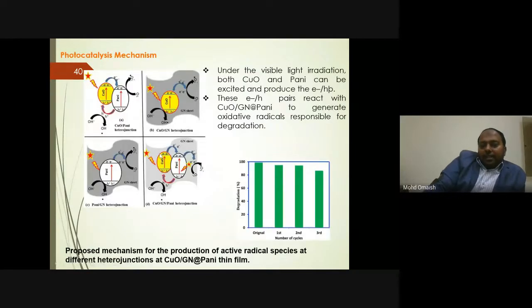As far as the photocatalysis mechanism, we propose four different types of heterojunction: the copper oxide polyaniline heterojunction, the copper oxide graphene heterojunction, the polyaniline graphene heterojunction, and the ternary copper oxide graphene polyaniline heterojunction, by which the transfer of electrons takes place. And we got very good reproducible results.